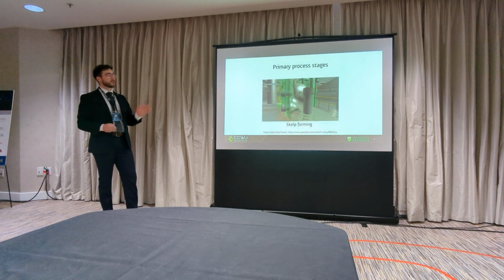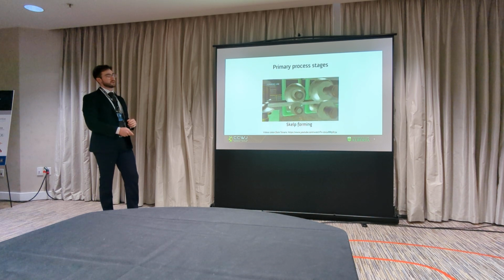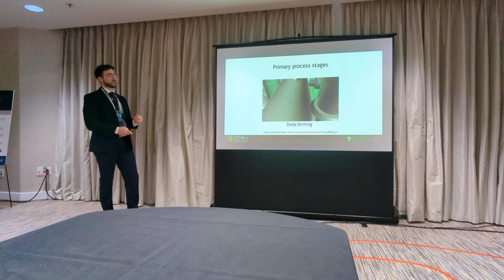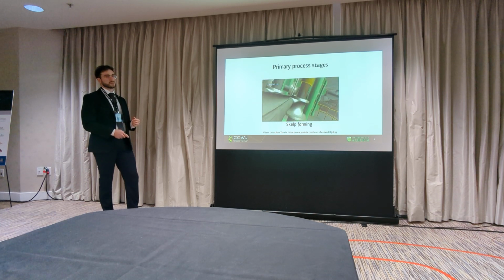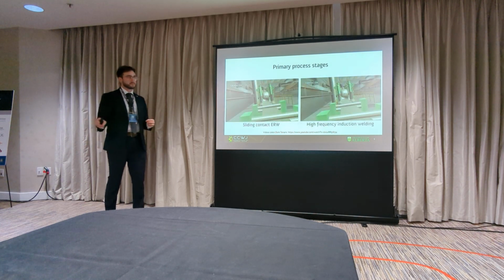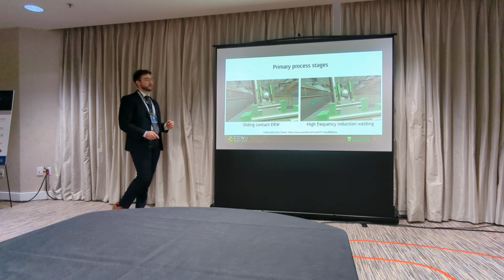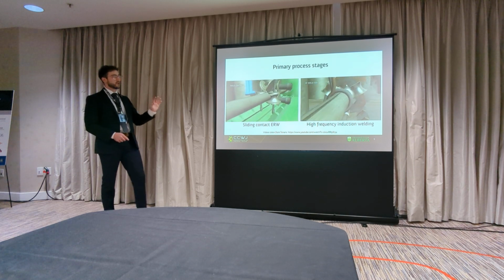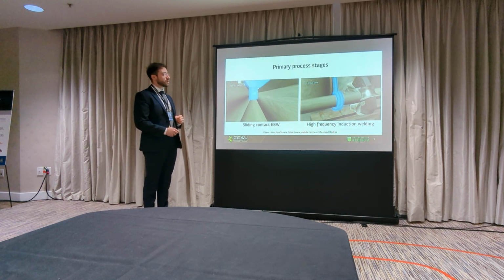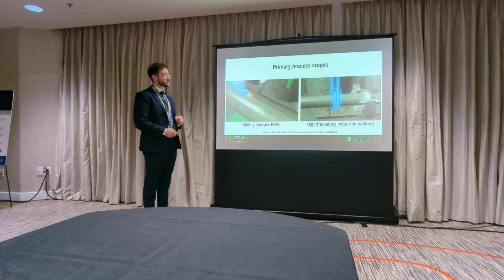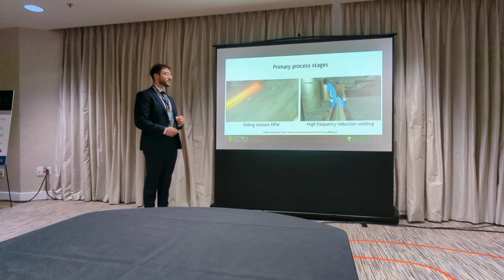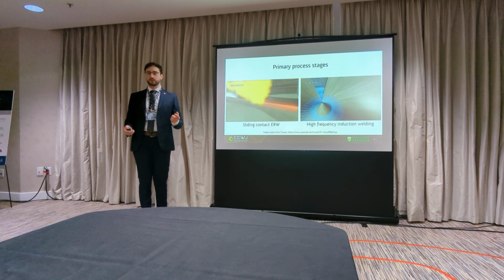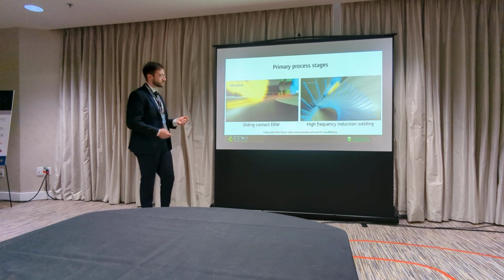So a quick video: you take an inlet coil of sheet material from a rolling mill and you feed it through some rollers. There's successive deformation to the point where you get a circular product, and then after the successive deformation, there's usually two types of ERW that you can have, either a sliding contact type or an induction coil type. Both of them, for all intents and purposes in this presentation, are going to do the same thing, where they are inducing current in a weld V, whereas you merge the two interfaces. Those interfaces heat up, there's sometimes a liquid film, and then there's physical upsetting between the two, and then you get a metallurgical bond. Yeah, they're pretty simple.